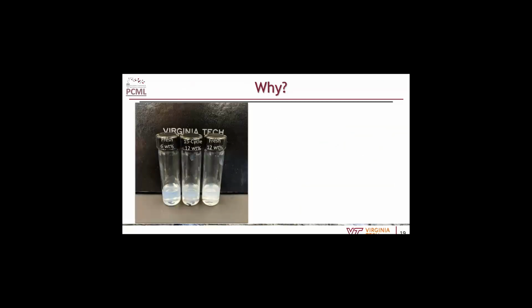So what we wanted to look at is why. Why is this happening? If you take a suspension of 6 weight percent and 12 weight percent, and you flip them over, the 12 weight percent will stay at the top of your vial because it's effectively a gel. Again, that's because of all the charges and all the cellulose nanocrystals repelling each other. They form liquid crystals of cellulose nanocrystals.